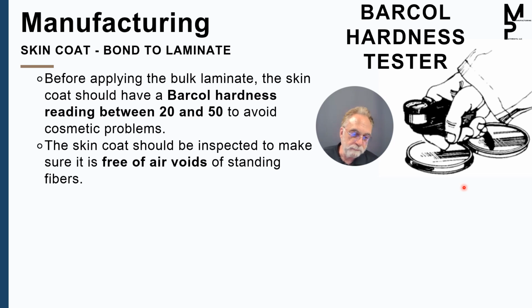But before we do that, we want to do an inspection. Because if I see any voids now, I can still see an air void between the skin coat and the gel coat. And if I catch it right as the skin coat cures and the laminate's still called green, it's not cured fully. It's hard, but it's not that hard. I can cut that air void out with a box knife, and I can fix it right then and there. Okay, it doesn't take 30 seconds. It takes 2 or 3 minutes, but certainly better than the hours it's going to take later on.